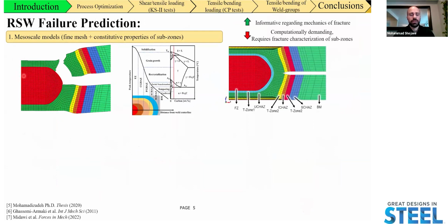all the subzones. So the issue is that we have a heterogeneity in terms of the peak temperature that is experienced in different regions of the spot welds. So for example, as we go from the fusion zone towards the base metal, we have different metallurgical transformations that are occurring because of that gradient in terms of the peak temperature. Now, this means that we're going to have differences in terms of mechanical performance of all the different subregions, as shown on the right-hand side here as well.